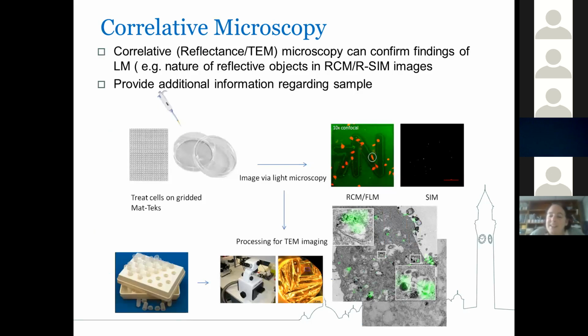So one of the challenges we faced in doing this was that as it's dehydrated, the cell shrinks a little bit. So it can be quite difficult then to find the same cell, because it might have changed shape and structure a little bit. So one of the ways we got around this was by using the gridded MatTek dishes. So you could at least find the same grid. So you would do your confocal microscopy first, note the grid of interest, and then do the TEM on the same grid reference point. We usually looked for cells that had some feature to them that would make them easily identifiable. So for example, there were two cells close together, or the cell had a particular flap on it, or something that would make it recognizable. And then we developed the code in MATLAB to overlay the images and restructure them.